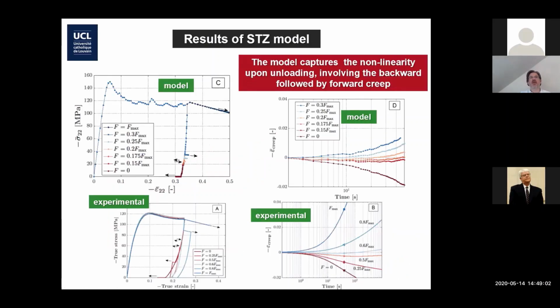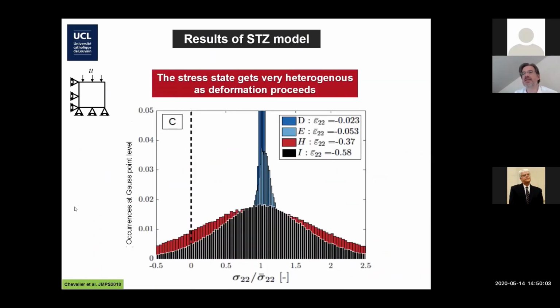The most important is this, and this was really the thing we were very happy about. You remember the experiments that I explained, where you have this forward creep under full stress, recovery, and this stagnation point here where you have backward and then forward creep. Guess what? The model, without any new tuning, is capturing this in a certain range. If you perform a creep test at something like 25–30% of the load, you're getting first backward creep, sort of recovery, followed by forward creep. And of course, it's not right to the point. Experimentally, we see this at 60% and not at 25%, whatever. The message is that the model is rich enough to capture a mechanism like that, and there are many, many improvements you can do, of course. And this has to do with this landscape of stress, heterogeneous stress development.